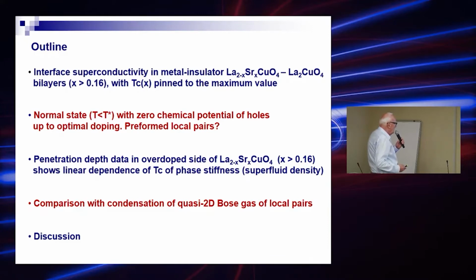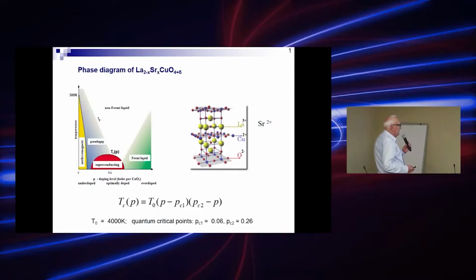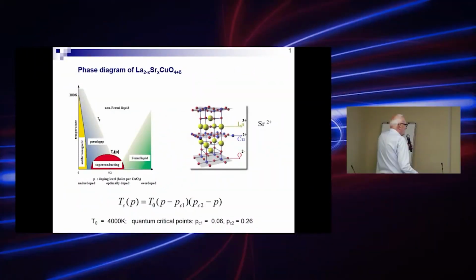And I'll give you some simplest explanations. This is simplest introduction to remind you about LSCO structure. Here is the phase diagram of LSCO. Here's the structure. Doping is given by replacing lanthanum by strontium or with extra oxygen. This is delta. And here we see the superconducting dome and nice empirical formula for TC as a function of doping level P.